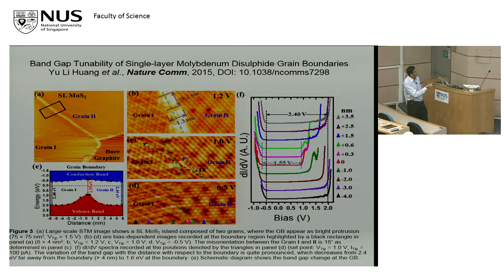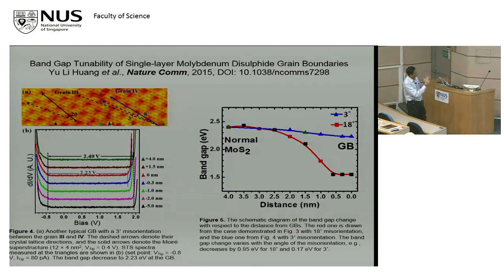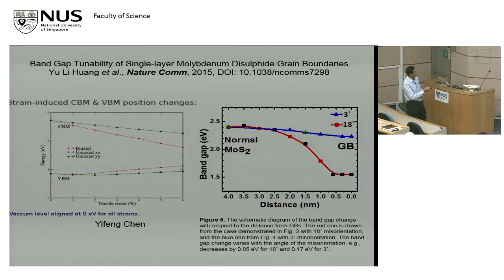And we also showed that at grain boundaries like this, the band gap, the electronic structure changes. If we did STM towards the grain boundary and away from the grain boundary, it shrinks, and there's some structure at the edge. And it was Kwek Suing's group that helped. This is a different angle. And Yifeng from Suing's group helped do some calculations to show that by having a few percent of strain, you can actually change the band gap by that amount. So we believe there's strain at the grain boundary. So you can alter and tune electronic properties through strain.